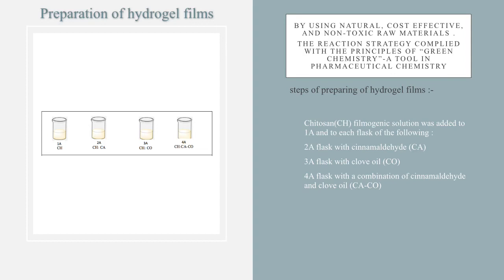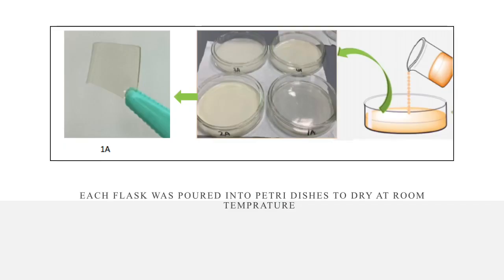The steps of preparing the hydrogel films are the following. Chitosan filmogenic solution was added to flask 1A and to each of the following flasks, as you can see in the figure. 2A flask with cinnamaldehyde, 3A flask with clove oil, 4A flask with a combination of cinnamaldehyde and clove oil. And here, each flask was poured into petri dishes to dry at room temperature.